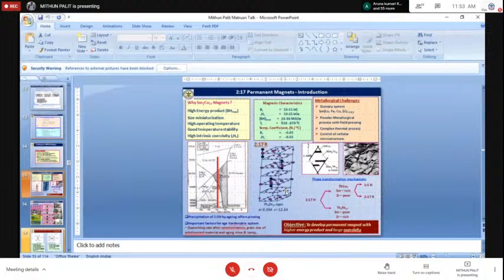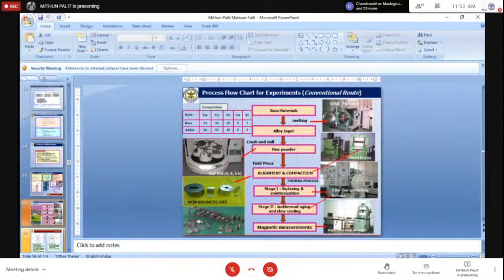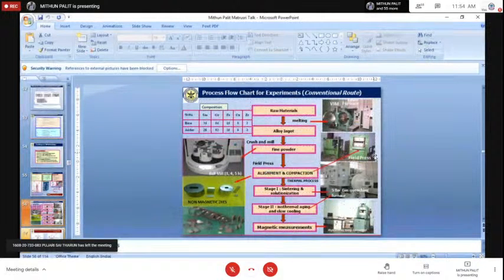And this 217 type magnet is also prepared by the powder metallurgy route. So the alloy is prepared by vacuum induction melting, followed by making fine powder using planetary ball mills, followed by orienting the powder. You see this green color machine is basically a very high power electromagnet, which helps the powder to get oriented in one particular direction.